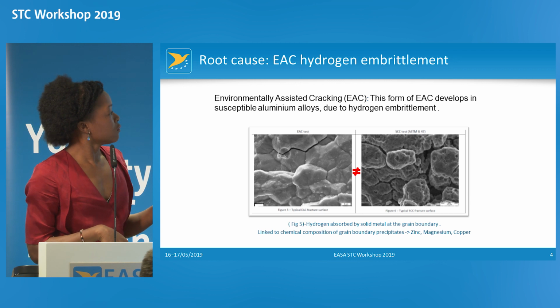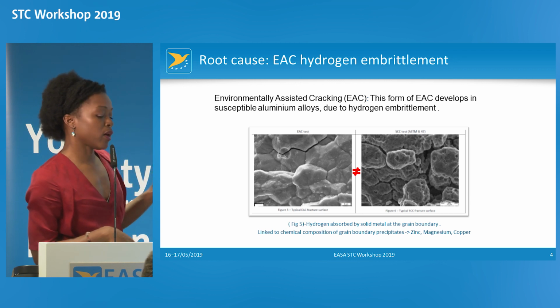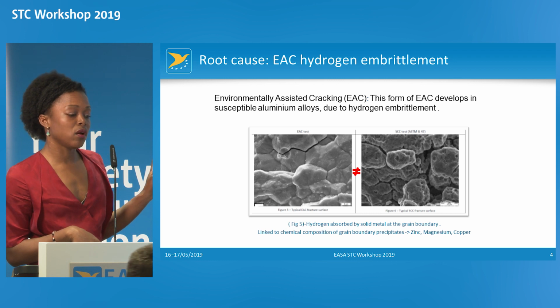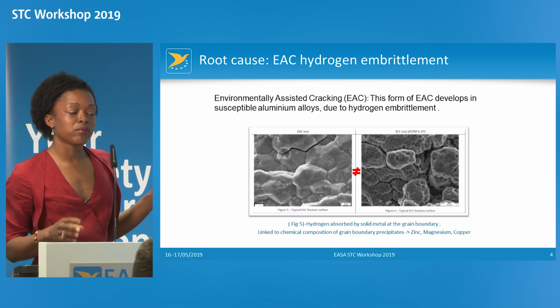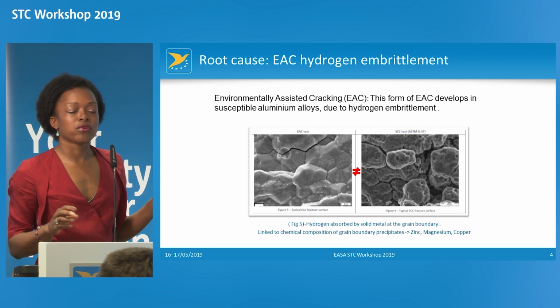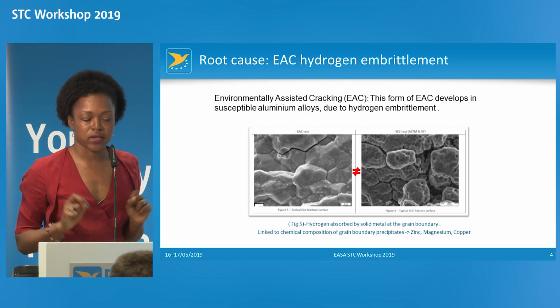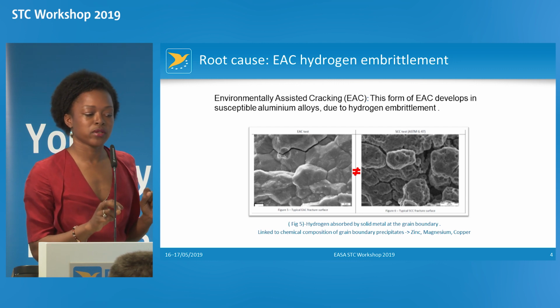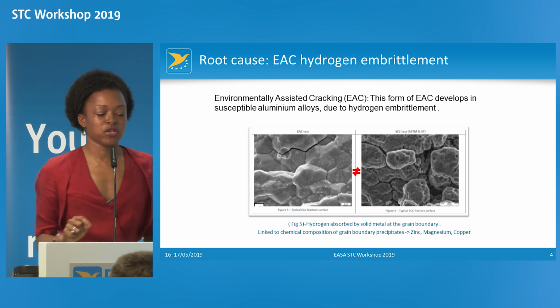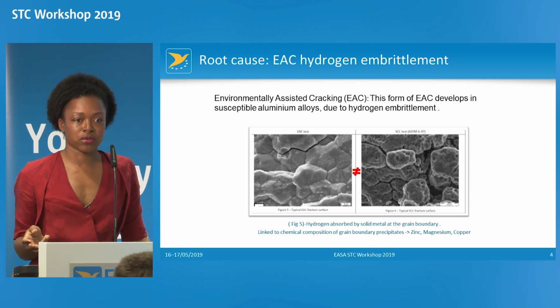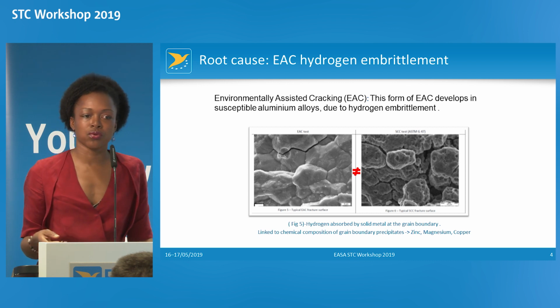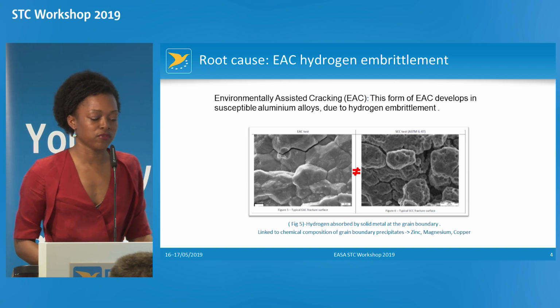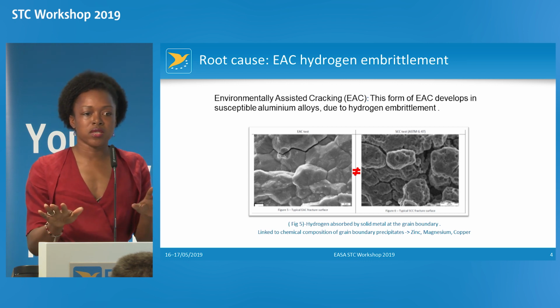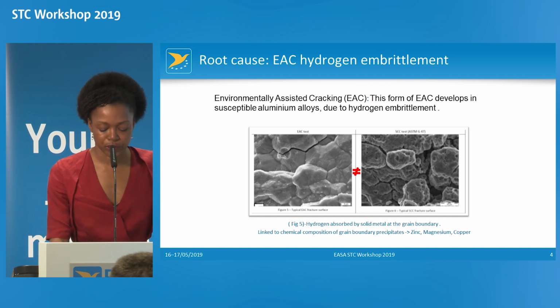When doing a fractographic analysis of the cracked material, you see those patterns. On your left-hand side, you have EAC, which is a failure at the grain boundary, while the grain itself is not so damaged. This is due to hydrogen embrittlement of the solid metal. The next picture is conventional stress corrosion, which affects not only the grain boundary but also the grain itself. So this is how EAC due to hydrogen embrittlement is differentiated from conventional stress corrosion.